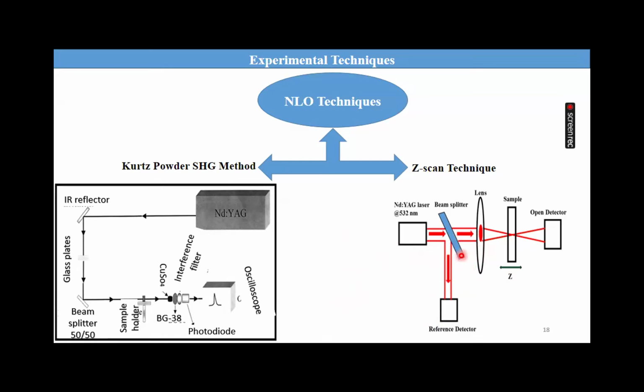In these experiments, it may be preferable to use materials with negative nonlinear indexes of refraction and thickness below the diffraction length, also known as the Rayleigh length of the focused laser beam. As a result, the aperture in front of the detector has a smaller spot size, resulting in better transmittance through the aperture. Due to the intensity, this impact gets stronger as the sample gets closer to the focus. The sample can transmit the most light through the aperture when it is just in front of the focus.